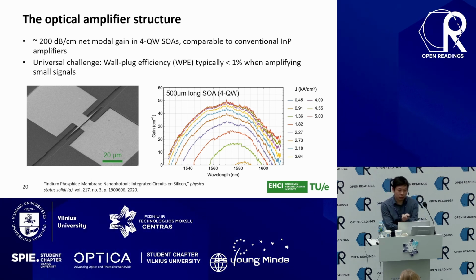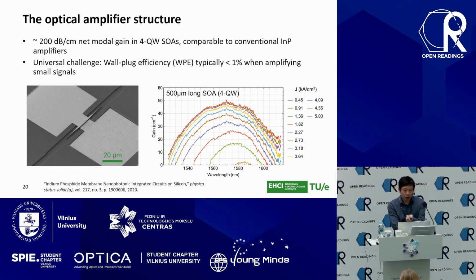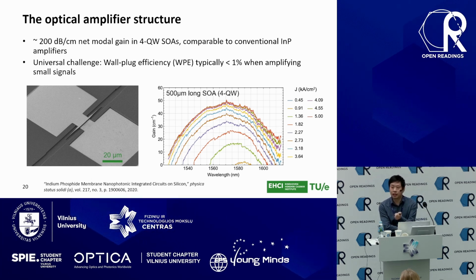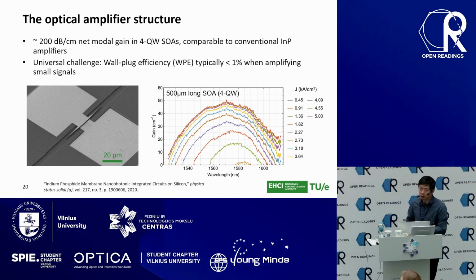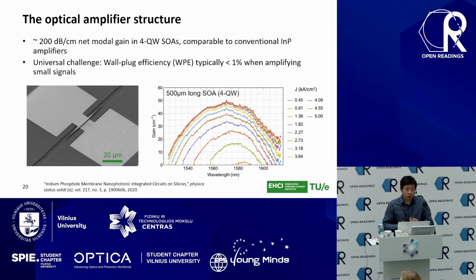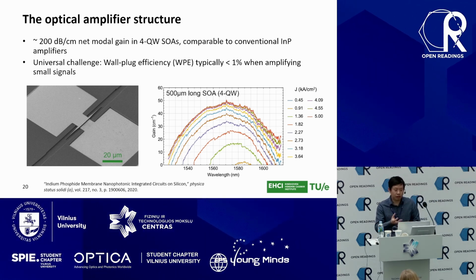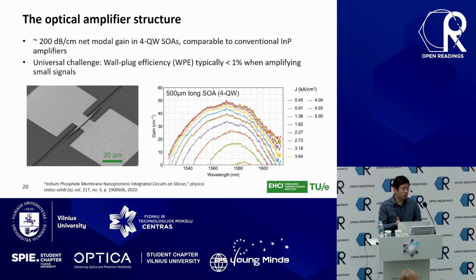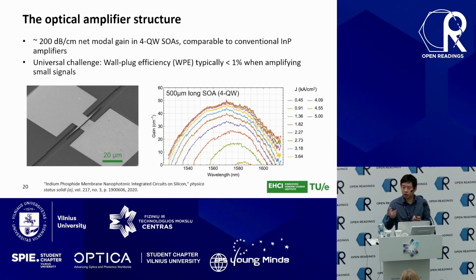But the point I want to raise here is a universal challenge. Optical amplifiers are intrinsically very poor in efficiency, especially if you want to use this device to amplify a very weak signal. For example, in an optical communication system, if you try to amplify a microwatt level optical signal to milliwatt, you need to pump your amplifier very hard. And then if you calculate the wall plug efficiency, it's less than 1%. So it means if you just buy a conventional amplifier and use it as is, 99% of the electrical power you pump in is wasted. Where does it go? Heat.